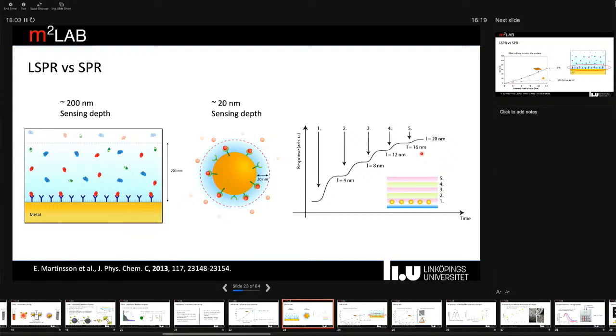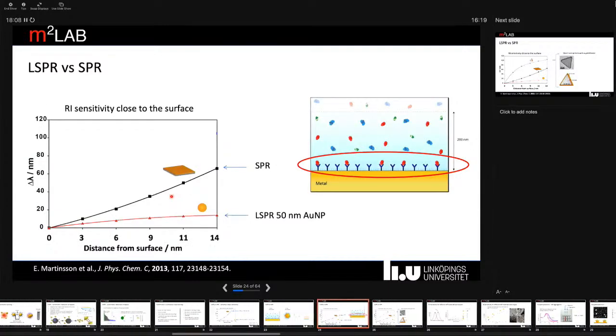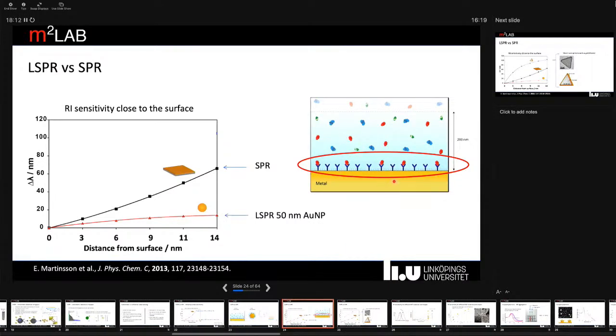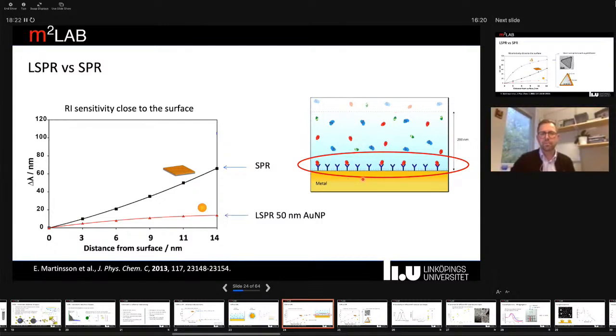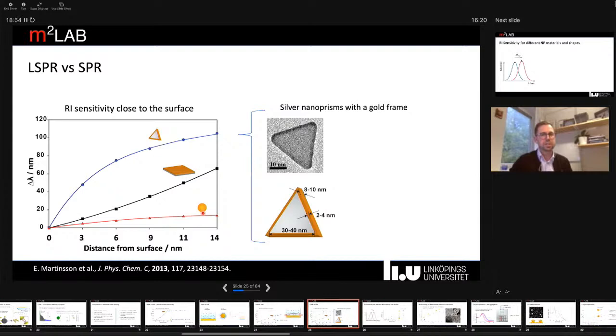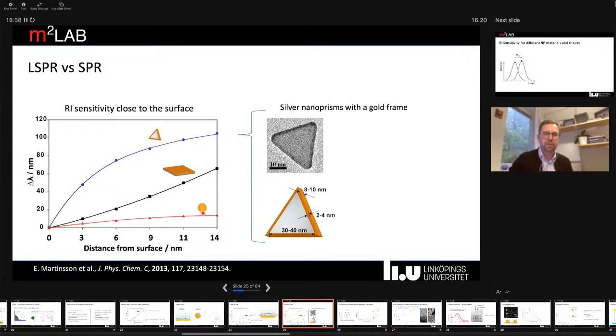So this is both an advantage and a limitation, as I can show you. The advantage, I would say, is that if you look here, most of the interaction actually occurs within this distance from the surface. So whatever goes on here, we're not typically really interested in, and that can actually just contribute to making the signal from the biorecognition event more difficult to interpret. So if we instead just look at what happens in the vicinity of the surface within 50 nanometers or so, we can see that there's not such a huge gap between these simple spherical 50 nanometer particles and SPR as the method. And by using some more sophisticated nanoparticles, such as these gold nanoframe protected silver nanoprisms, we can actually outcompete SPR, at least within the first 20 nanometers or so from the surface.